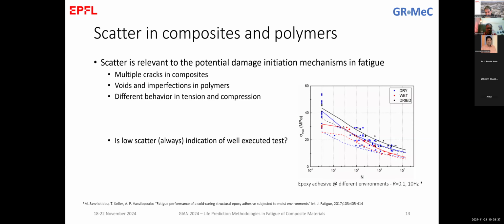But the red points are in between these points. But we can see that the red curve is well below the blue curve. So how is it justified actually? Although we can see the curve fitting, the R square value maybe is not mentioned here, to say that it is giving a good fit. But even then, for a particular stress level, we cannot say that the data is statistically significant.